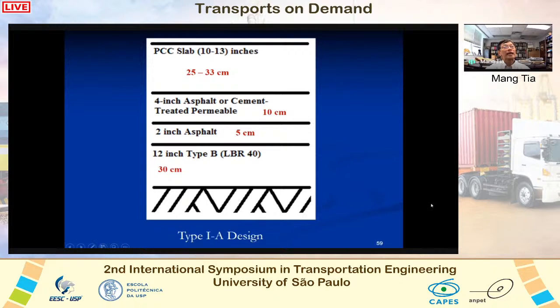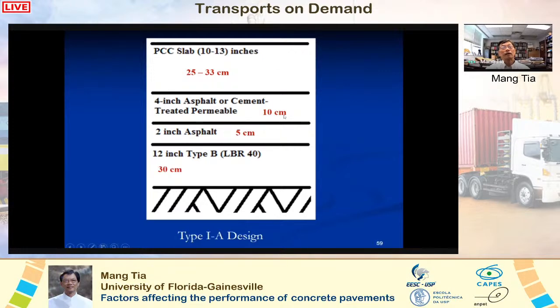The 3 designs evaluated were designated as Type 1A, Type 1B, and Type 2 in this study. This is the Type 1A design. It has a PCC slab of varying thickness, 10 centimeters of asphalt treated or cement treated permeable base, 5 centimeters of structural asphalt concrete, and 30 centimeters of a stabilized subgrade.